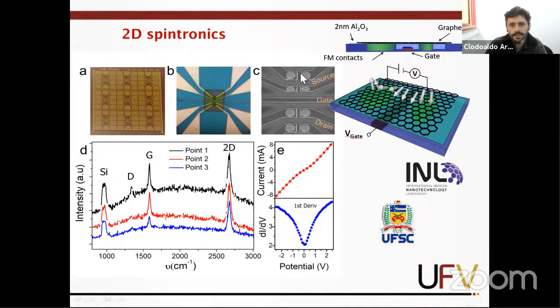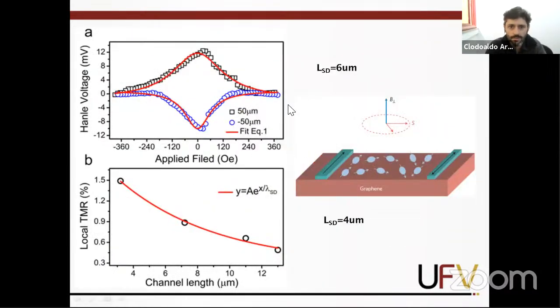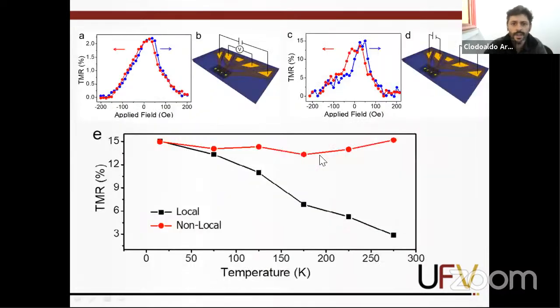And then by using these vortex configurations, we can achieve the anti-ferromagnetic configurations needed for zero field. And with help from the INL, we developed a very nice epitaxial graphene. Then we could do microfabrication to have lots of devices. And then we could characterize the spin transport in this graphene, with a very long spin diffusion length, like 6 micrometers. And we could then first characterize this magnetic resistance and spin transport at room temperature. That was the first measurement made in this way.